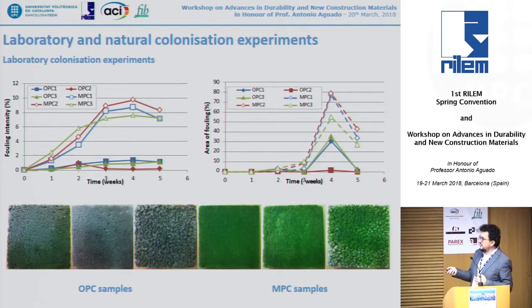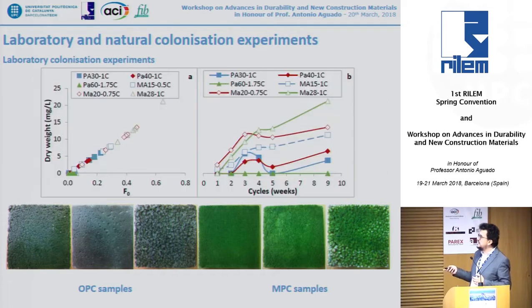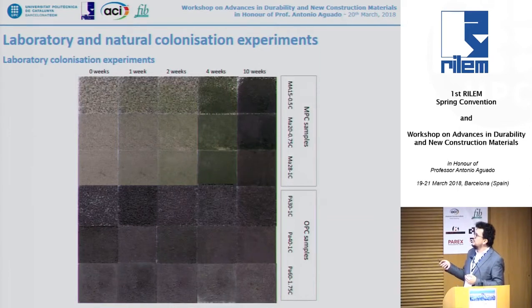So we have here the OPC samples and the MPC samples. And also, at the end of the test, the dry weight and the CO2. What we have seen is that the MPC samples were colonized earlier than the OPC samples, and to a larger extent. So the presence of this different pH material and also the roughness of the materials allowed us to have a larger colonization in our samples. This is an image of the whole exposure that we made with different roughness, controlling the colonization of the different samples.